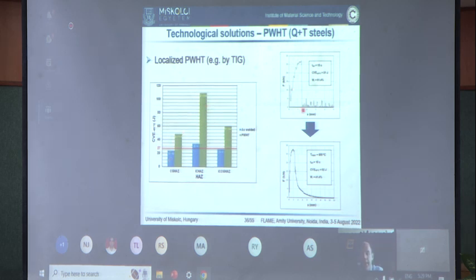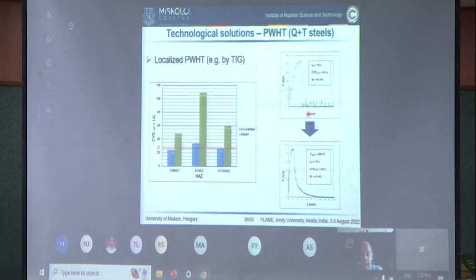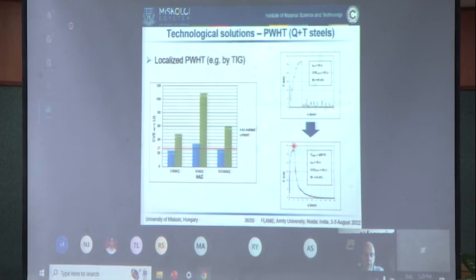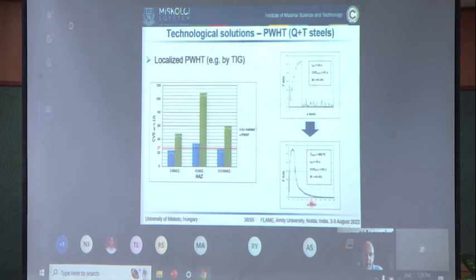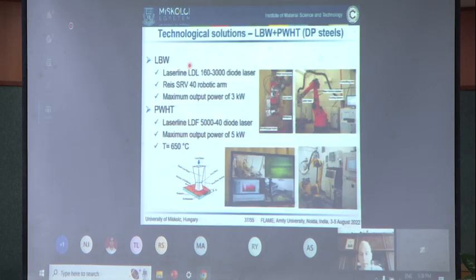You can also see it in the graphs. This was the original intercritical heat affected zone force displacement diagram during impact testing, and this one is the force displacement diagram after post-weld heat treating. You can see that the intercritical heat affected zone behaves fully ductile after this localized post-weld heat treating.